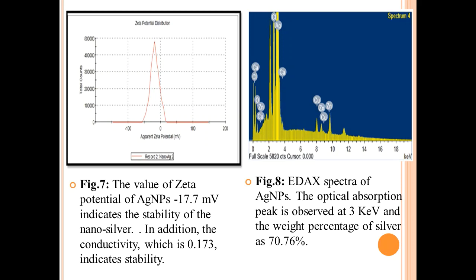Figure 7, the zeta potential value of silver nanoparticles, minus 17.7 mV, indicates the stability of the nanosilver. In addition, the conductivity, which is 0.173, indicates stability. Figure 8, EDX spectra of silver nanoparticles. The optical absorption peak is observed at 3 keV, and the weight percent of silver is 70.76%.